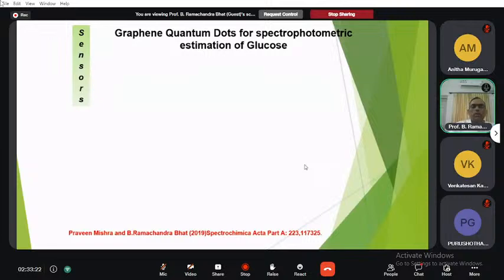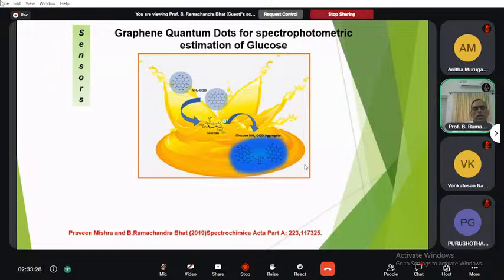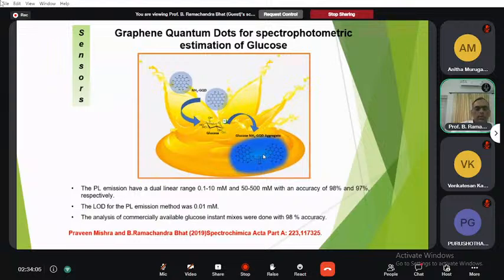Then we have taken the quantum dots for a spectrophotometric estimation of the glucose. So quantum dots is taken, and you can see how the quantum dots help here in sensing the glucose. So this is the quantum dots, and it is functionalized with amino functionalized material. So this is the amino functionalized graphene quantum dots. When it reacts with the glucose, see these two pieces of the quantum dots, it is joined through this, and thus you can see the glow here, and this is the photoluminescence emission